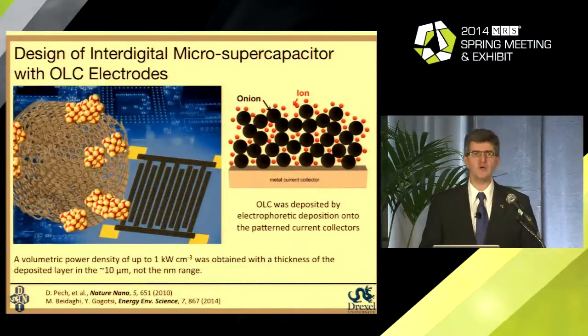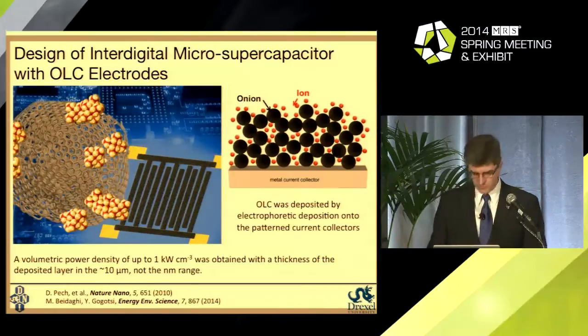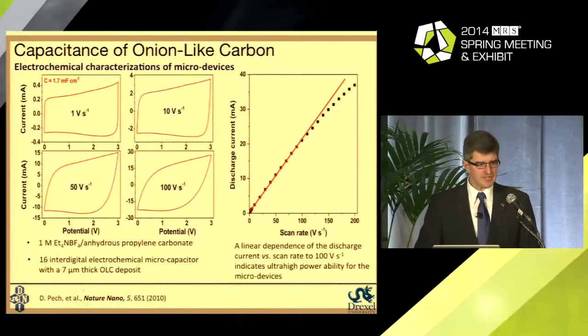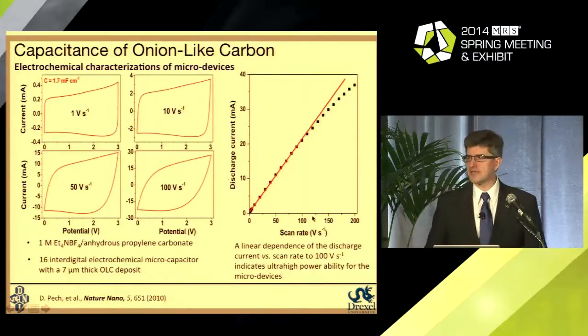So, how can we solve the problem? How can we make a device that can be really quickly charged in all the area used here? We can use different carbon materials. We can use, for example, multi-shell fullerenes, carbon onions, or nanotubes, which don't have internal porosity. All the accessible surface area is on the surface of these particles here. And if you make a device using, for example, carbon onions, you can charge those devices with rates going up to 100 volts per second. You see, up to 100 volts per second, we get a linear dependence of discharge current on scan rate here.